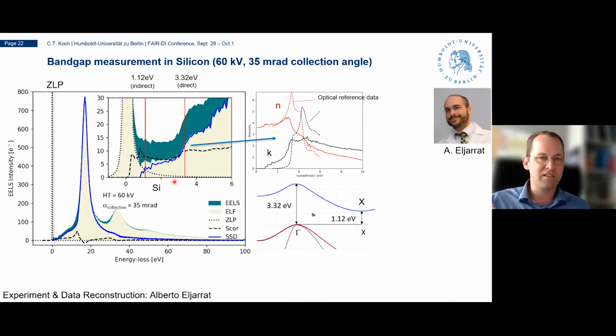So this is some data that Alberto Eljarrat from my group acquired on our microscope, which has a very good resolution in EELS. So this is the zero loss peak, for anyone who knows about EELS. It's monochromated, so it has a very well-defined primary beam energy. And this is the plasmon peak. But what we're interested in is, can we map the band gap in silicon? And that is always a challenge for these electron energy loss spectroscopy experiments, because the band gap of 1.1 eV and the very weak signal make it difficult to separate from this zero loss peak. So what you see here is the zero loss peak. That is in principle this very sharp peak that you see here, only blown up. Basically, this small area down here is blown up.